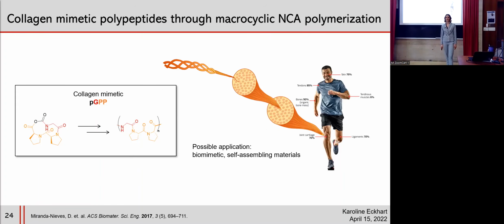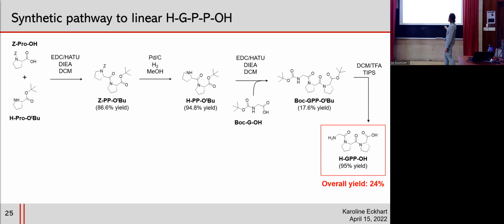So our first target for this project was a collagen mimetic protein. For the reasons I stated above, this could be an interesting biomimetic material as an implant. So we started out by creating the glycine proline proline amino acid trimer through a 4-step synthesis. And our overall yield here was about 24%. And I want to point out here that the yields of each of these reactions was pretty high, except for this one here. So that's a future direction that we're working on.